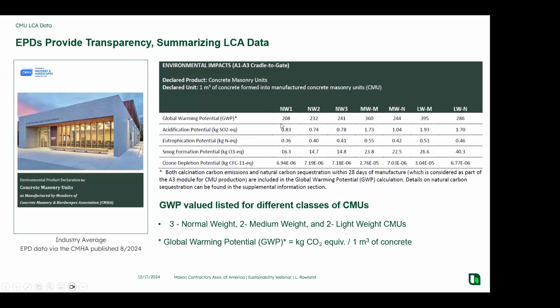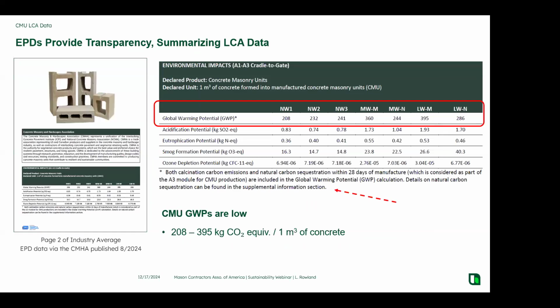You have GWP of only 208, and then the top GWP is up here at 280, or excuse me, 395 is the highest. That's the lightweight block. So you can see the different materials, and that's the range of the GWP associated with these. Quite low compared to cement, of course. They are in line with some concretes. They tend to be lower than typical concretes, of course.